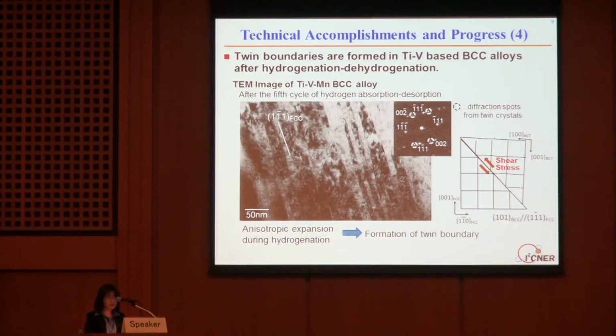Titanium vanadium manganese BCC alloys have a hydrogen capacity of over 3 weight%. So this is one of the best candidates for mobile hydrogen tanks. In these titanium vanadium BCC alloys, twin boundaries and stacking faults were formed after hydrogenation and dehydrogenation. These BCC alloys transform to FCC hydrides, so in order to accommodate shear stress, twin boundaries form.